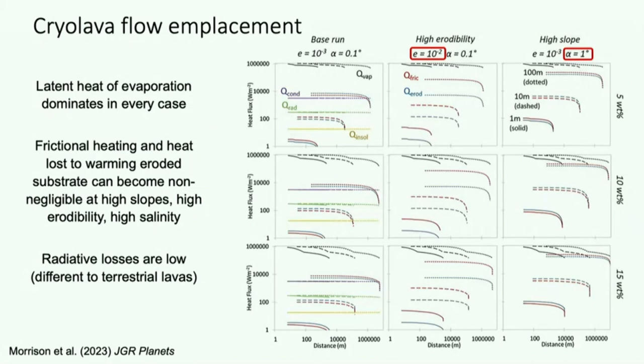Okay, so this one's a little hard to explain, but basically each of these lines tells you about a heat flux, and the lines stop whenever the turbulent to laminar transition was reached. So the end of the line means that's the end of the flow. And the reason that there are so many different lines on there is we have 100 meter thick flow, 10 meter thick flow, 1 meter thick flow. And we have it for different salinities on the different rows. And then we have a base condition, one with high erodibility of the substrate and one with a steep slope. And obviously, if you've got a slope of 1 degree, you can't actually have a lava flow that's hundreds of kilometers long with a slope of 1 degree, because you need quite a bit of topography to make that physically possible, and that doesn't exist on Europa.